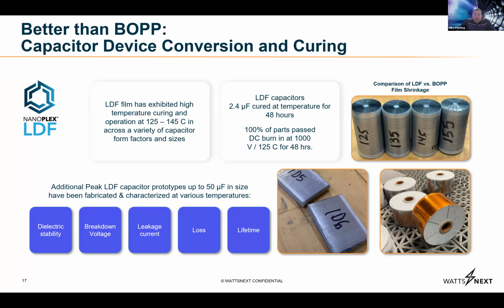And if you see the part at the very right of that picture, on the top flat surface, you can start to see a little bit of cracking in the end spray because of the shrinkage of the part. So these parts are, again, polypropylene replacements that operate a solid 40 degrees higher C than polypropylene could ever do at severe derating. And again, it holds at the larger part sizes as well.